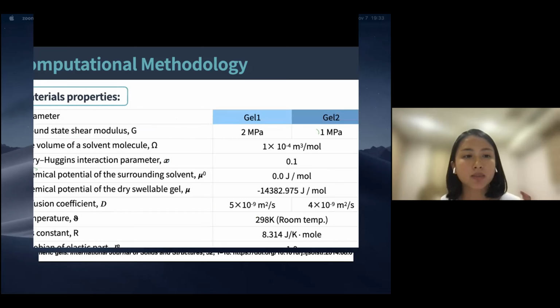And this is the material property we use in the calculation. Here there are two types of hydrogel property due to the different concentration of particles. The first type was the pure hydrogel, which is denoted by gel 1. And the second type was the particle cluster gel. We denote it by gel 2. In gel 1 and gel 2, the properties are the shear modulus and the diffusion rate.